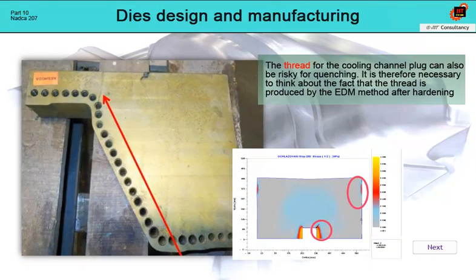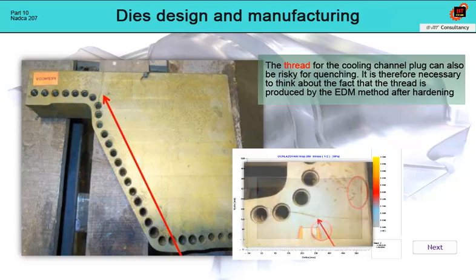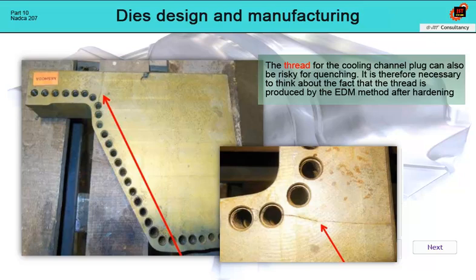This picture shows a hot forming tool. The cooling channels are close to the surface and have the task of cooling the surface so intensively that the formed sheet hardens. Their number cannot be reduced or the holes cannot be moved further from the surface. Therefore, there is a great risk of cracking during hardening, especially if sufficient attention is not paid to the machining of the thread. The thread is only used for screwing in the cooling channel cover and has no other significant function, but the thread is a source of notch stresses.